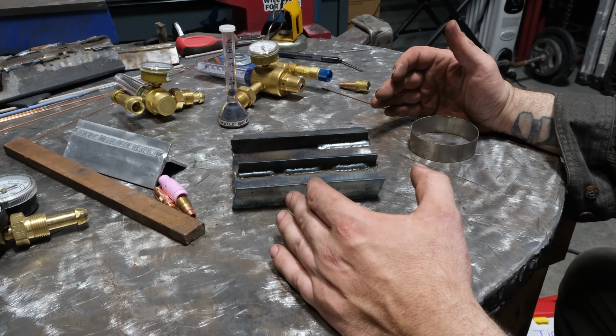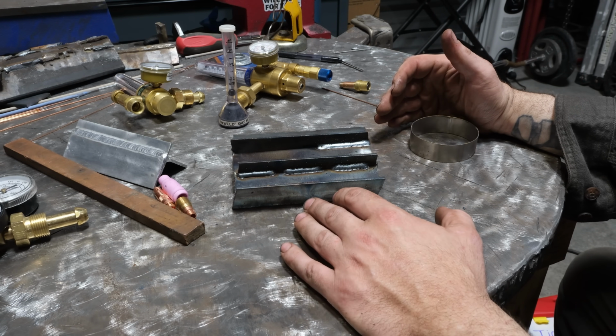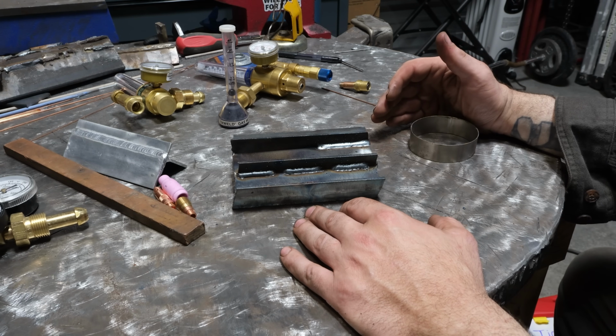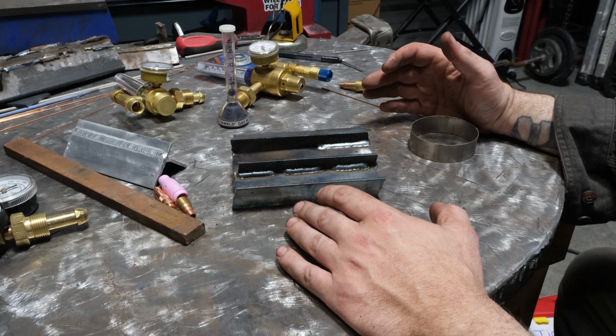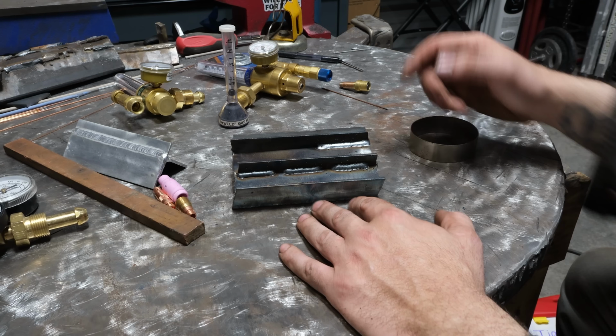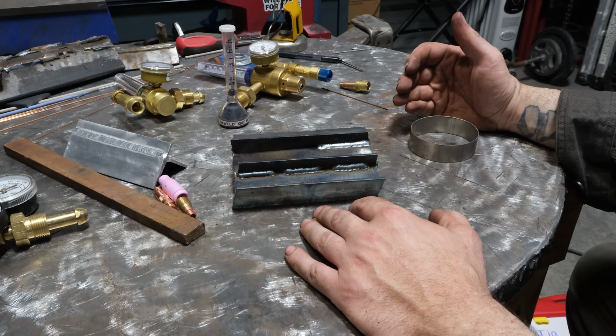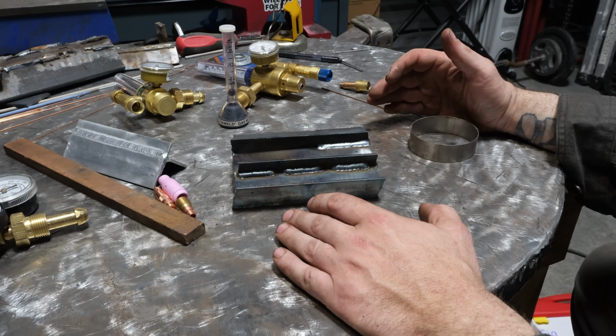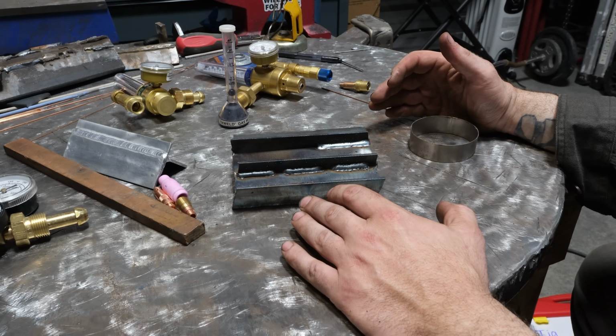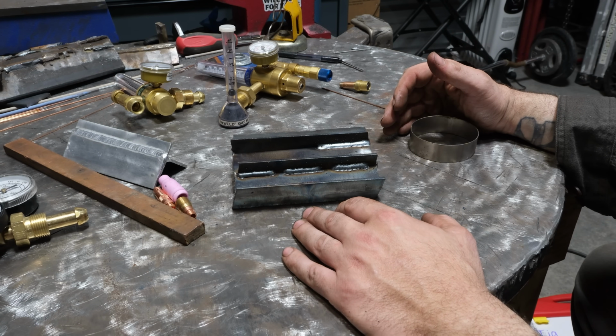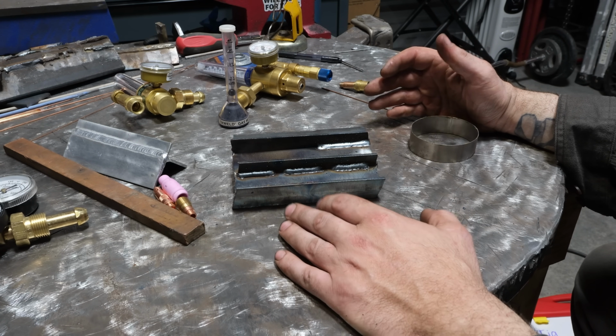If you're already at like 20 cubic foot an hour and you're seeing weld defects, you probably have a leak, the wrong shielding gas, or your flow meter's trash. So at 20 cubic feet an hour on a flat or a fillet weld, you should be able to make decent looking welds. Something else is wrong if you're having issues with that, like the wrong polarity, for example.